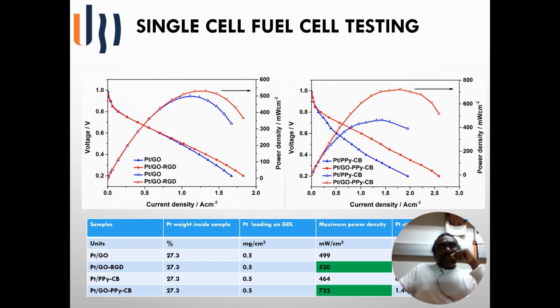As you can see, the maximum power density which we have obtained is 530 for RGD functionalized graphene oxide, and 722 for the hybrid material with graphene oxide, polypyrrole and carbon black. The main difference here is that polypyrrole is the connecting polymer, and polypyrrole has more nitrogen groups. These nitrogen groups always act as a ligand with metal nanoparticles. Maybe that could be the reason we could see the maximum power density for the hybrid material, and even for RGD functionalized graphene oxide too. You have got very high maximum power density.